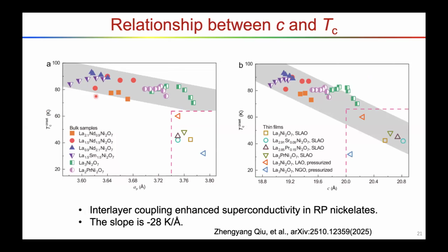If we plot the transition temperature as a function of the in-plane lattice constant and the C lattice constant, we found the TC has a linear relationship with the C lattice constant. The data in this part are from thin film samples. They all follow the same trend. So a simple conclusion is that the interlayer coupling enhances the superconductivity in RP nickelates, and the slope is minus 28 Kelvin per angstrom.